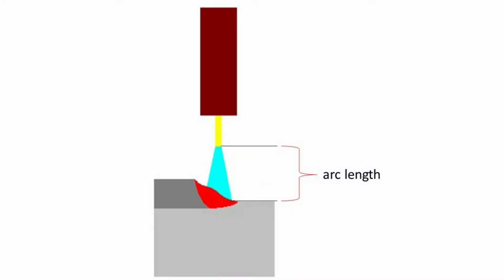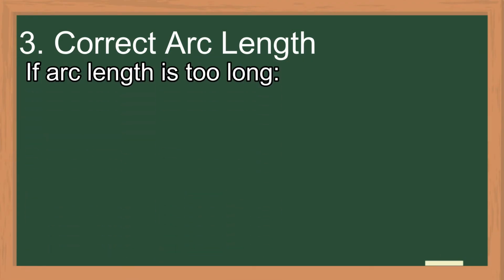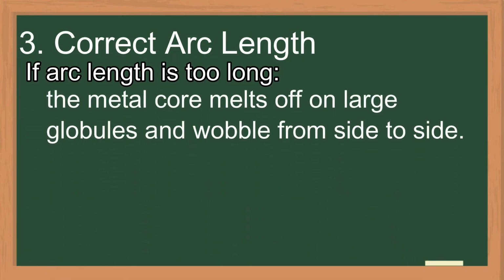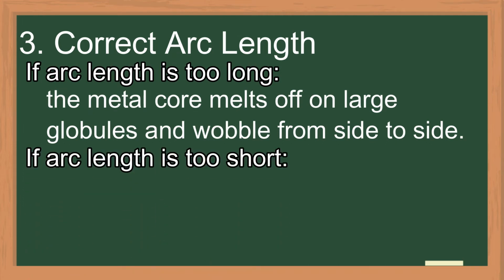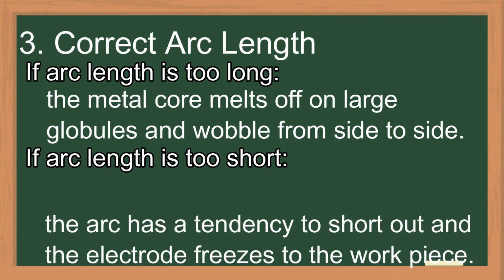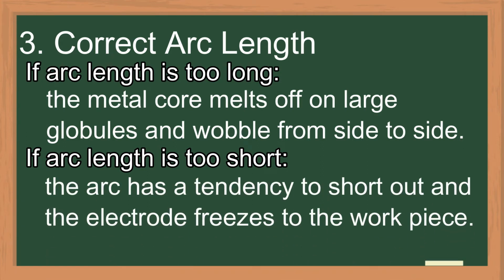Number 3. Correct arc length. Arc length is the distance from the tip of the electrode core wire to the weld puddle. If the arc length is too long, the metal core melts off in large globules and wobbles from side to side. If the arc length is too short, the arc has a tendency to short out and the electrode freezes to the workpiece.